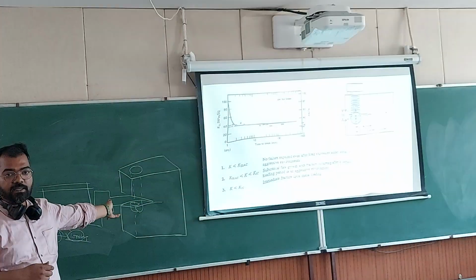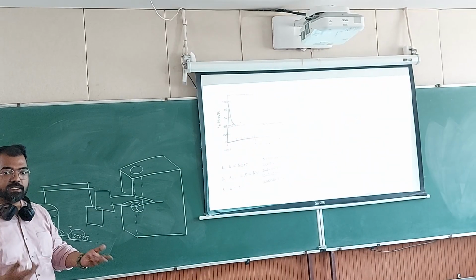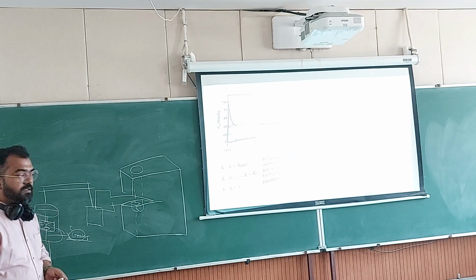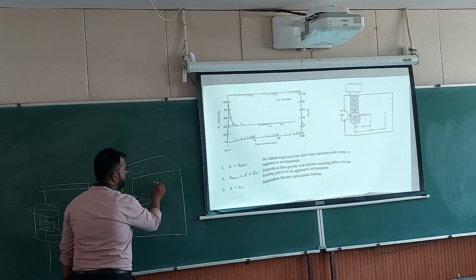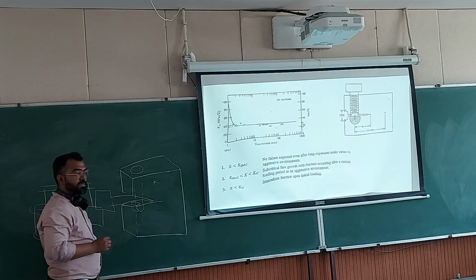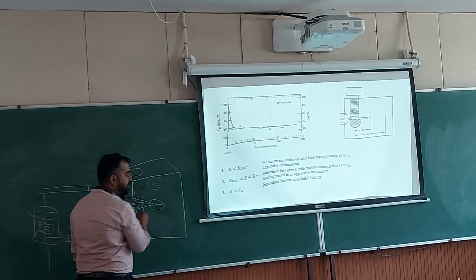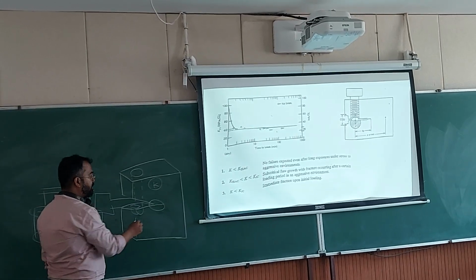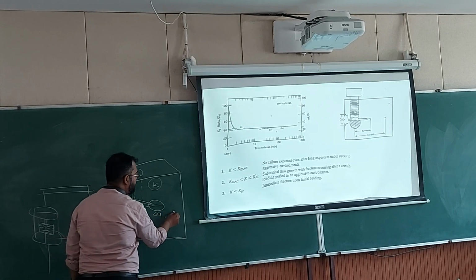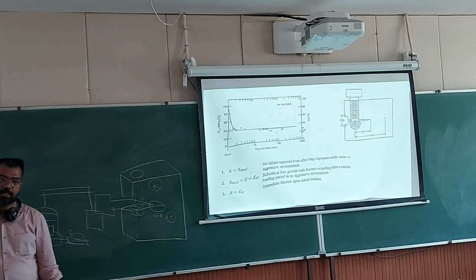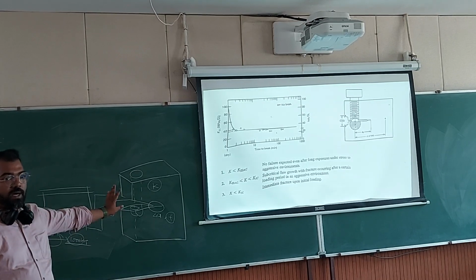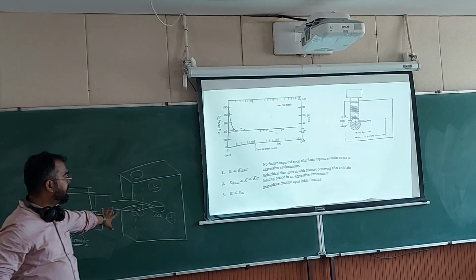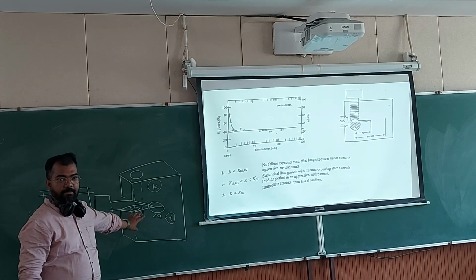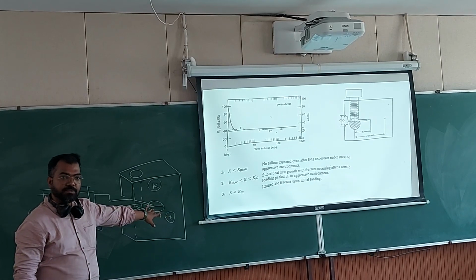To ensure that, you can again measure COD and find out how much stress is there, and the stress will be 0. If the stress is 0, then it is not going to grow anymore. Okay. So you started with some K value, and you know how much crack growth has happened. So you know the amount of delta A, and you know the amount of time it has taken for that much amount of delta A. And from this one specimen, you can calculate KTH, right? Because this will stop at KTH.